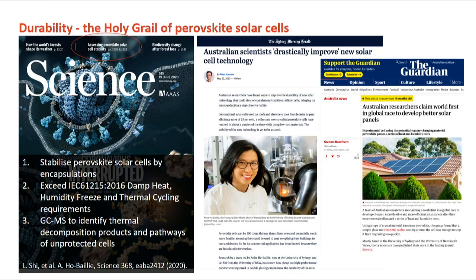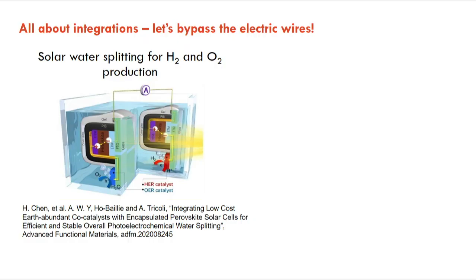So it turns out our cells actually perform better than the requirements by the IEC standard. Another breakthrough is we use this technique called GCMS to look at how cells degrade if they're unprotected. Why is it important? Because if you don't know how cells degrade, you don't know how to protect them. At the moment, we've got another project where we look at 3-junction tandem. We're stacking perovskite on perovskite and onto silicon.